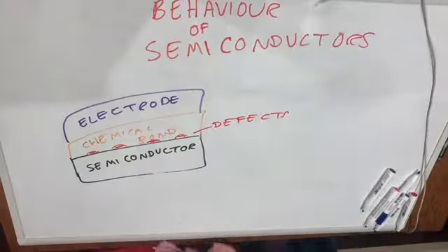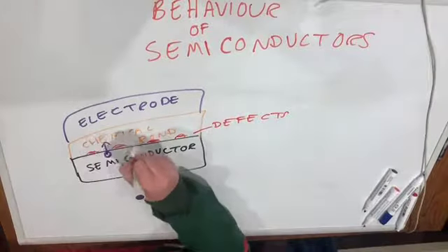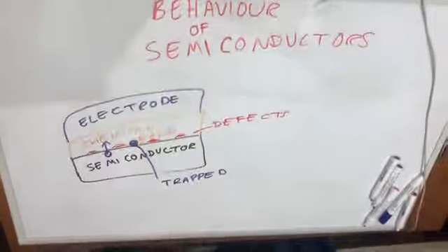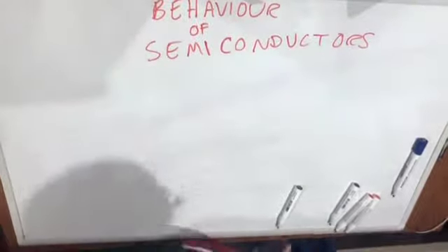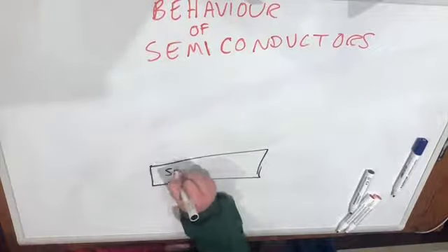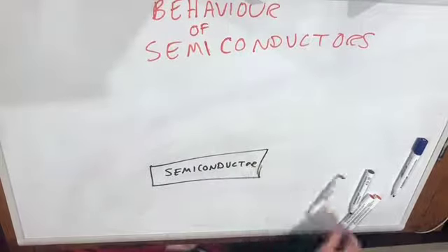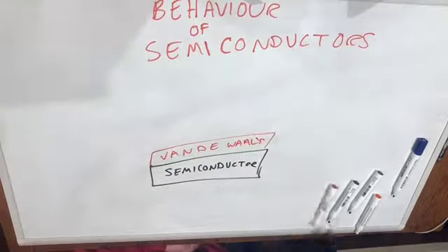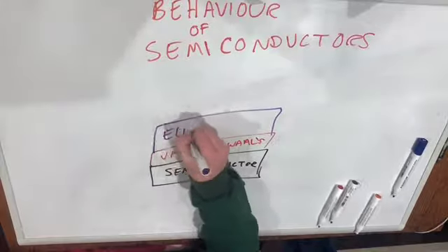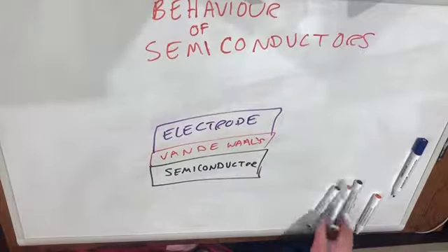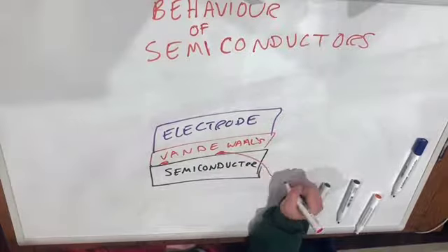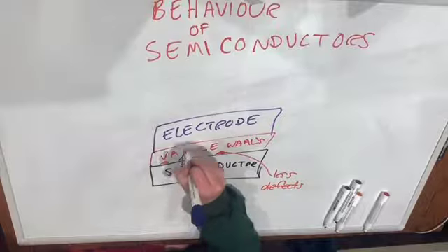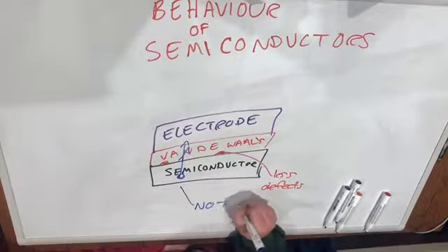The electrodes in semiconductor-based devices are what enable electrons to travel to and from the semiconductor. The electrons can carry computing information or energy to power a device. The UCLA method prevents the defects from forming by joining a thin sheet of metal atop the semiconductor layer through a simple lamination process. And instead of using chemical bonds to hold the two components together, the new procedure uses van der Waals forces, weak electrostatic connections that are activated when atoms are very close to each other, to keep the molecules attached to each other.